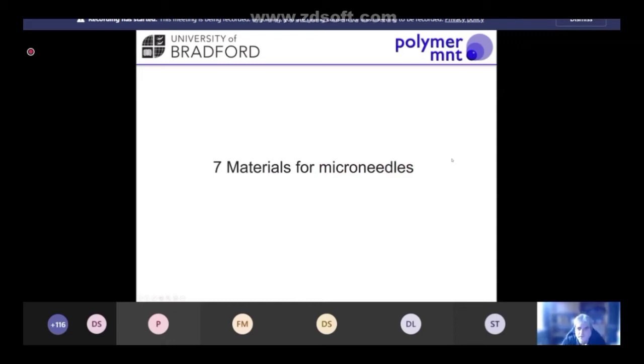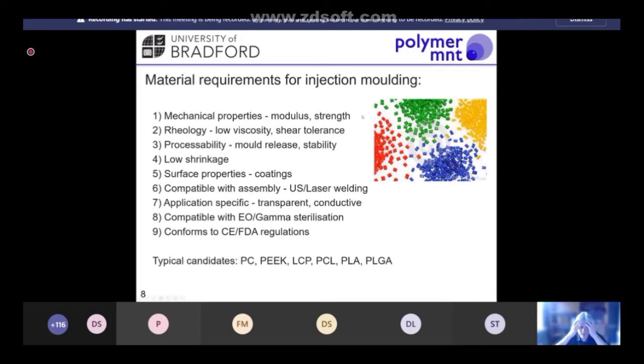So once we've defined what shape our microneedles are going to look like, we then need to make the rather challenging choice of what materials we need to use for these microneedles for a given application. So if we're looking at injection molding as a process, we need to look at our material behaviors. So we need to look at mechanical properties like the modulus and the strength of the microneedles, because that's going to basically influence entirely the penetration behavior of these needles into the skin.